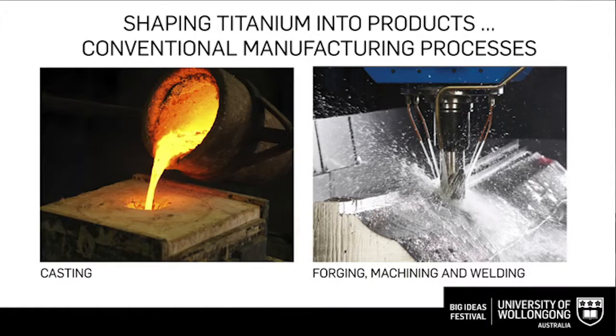If we look at the conventional processes used to shape titanium, casting is one where we melt the titanium in a furnace, cast the molten titanium into a mold, and then the titanium solidifies to assume the shape of the mold cavity. Now, titanium is very reactive to the atmosphere, so all of this has to be done in vacuum, which makes it more difficult to successfully cast titanium.